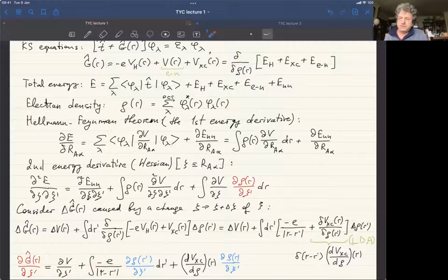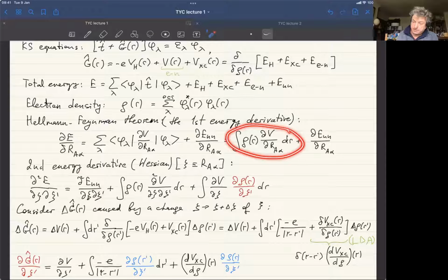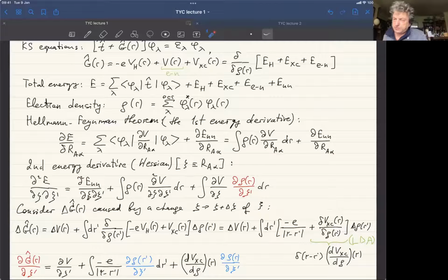But if we want to calculate vibrational frequencies, the situation is more complex. If we take the second derivative of the energy with respect to atomic positions, so I use ξ for the atomic positions for brevity, I will, of course, need to differentiate again this term, which is here. But then I will have to differentiate that term. And in that term, there are two terms which actually depend on atomic positions. This is the electronic density itself and that derivative of the potential with which nuclei act on the electrons. Taking the second derivative of that potential, no trouble. We can do this. This is just a sum of certain Coulomb and pseudopotential terms, so we can differentiate it explicitly and calculate these integrals in the basis set we have.